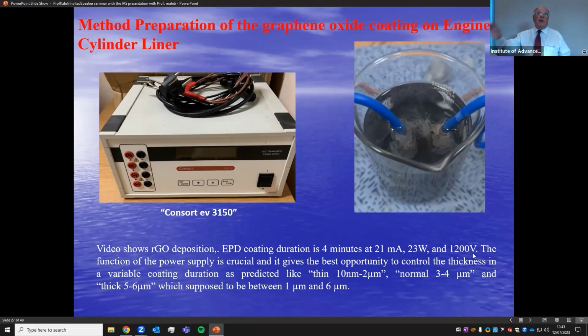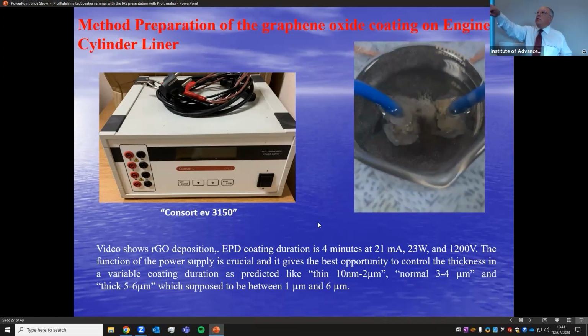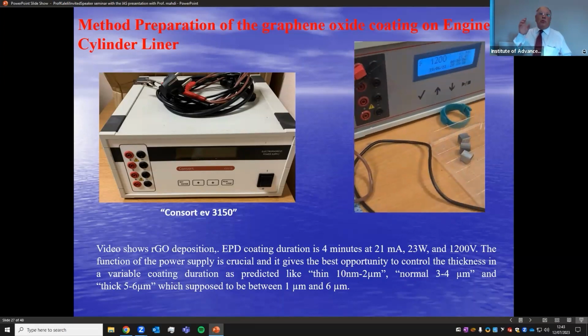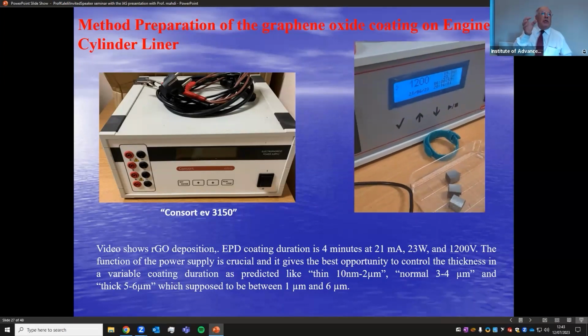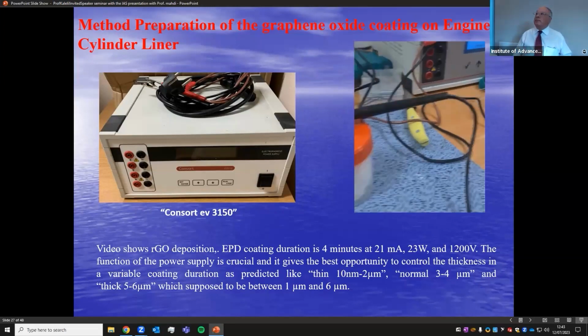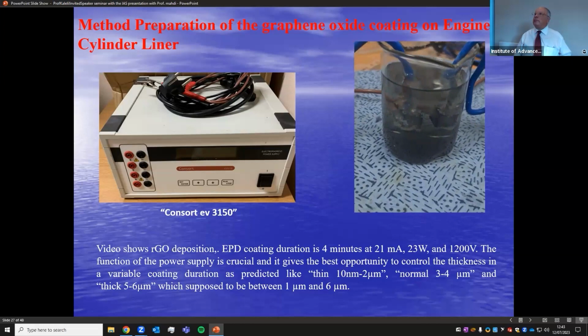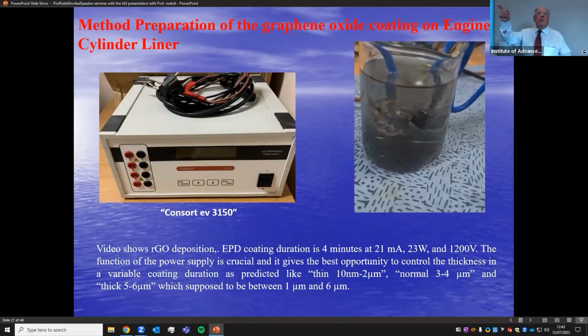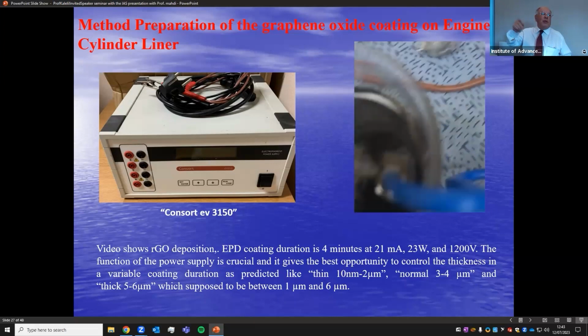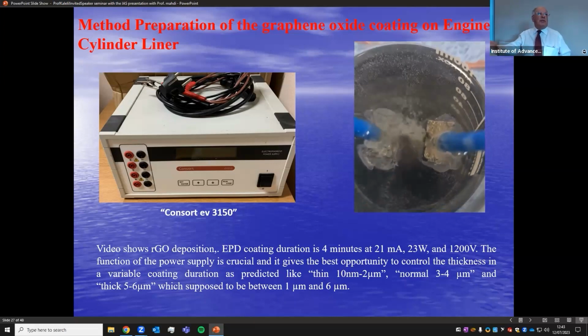Yes, the voltage in our lab is variable. So for example, in this process we used 4 minutes, 21 milliampere, 23 watt, and 1,200 volts. So you can see here. You see the coating process, and to be able to coat, we isolated the pieces of liner. If you see bubbles at 1,200 volts, then you understand you will be successful.